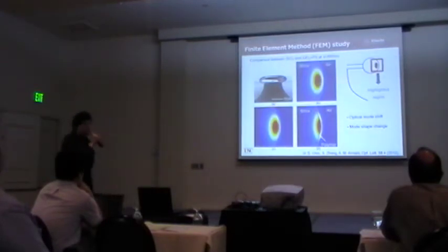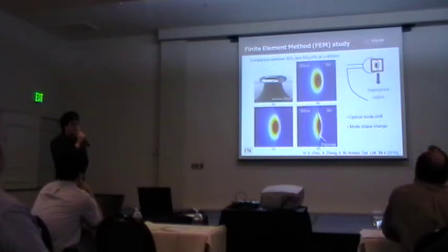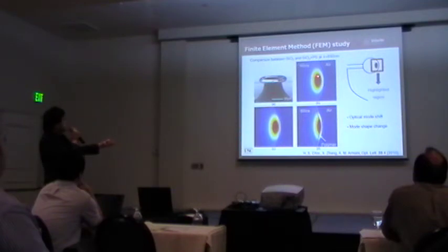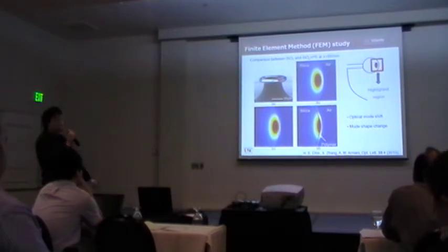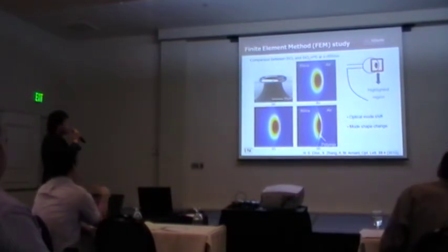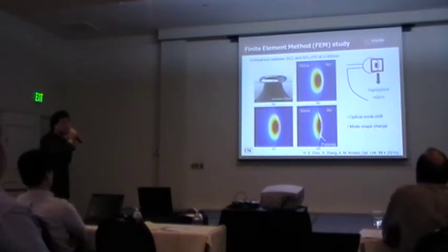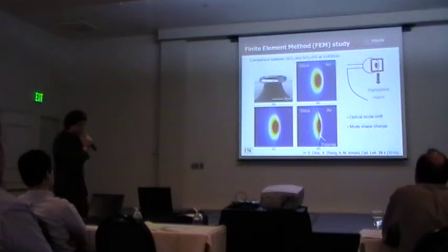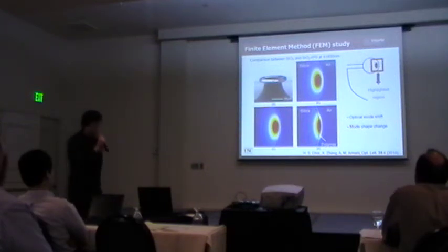For the theoretical study, we use COMSOL Multiphysics, which is finite element analysis software for modeling and simulations of any physics-based systems. In this slide, we can see a SEM image of a fabricated silica microtoroid and FEM result of silica microtoroid and 100 nanometer, 200 nanometer thick polystyrene hybrid devices at lambda equals 850 nanometers. This optical field distribution corresponds to a highlighted region on this drawing, and it is important to recognize from this FEM result that there is an optical mode shift, a mode shape change with a polymer coating, because the polymer with a higher refractive index than silica acts as a perturbing layer.